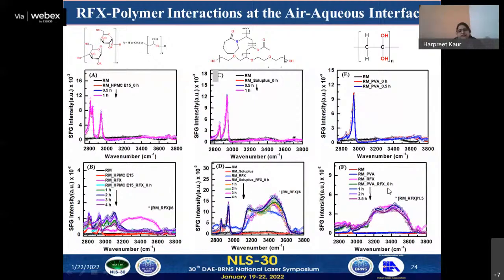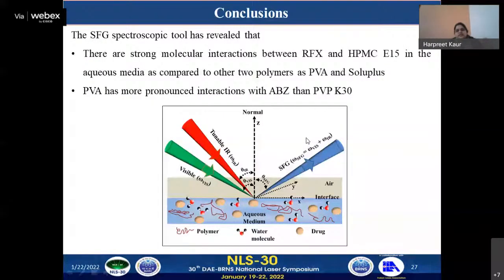In the case of the second drug, the PVA polymer effectively binds with this drug, as seen from SFG at the aqueous interface. So I can confirm here that the SFG study is very helpful in proving the interaction at the air aqueous interface in these drug polymer systems.